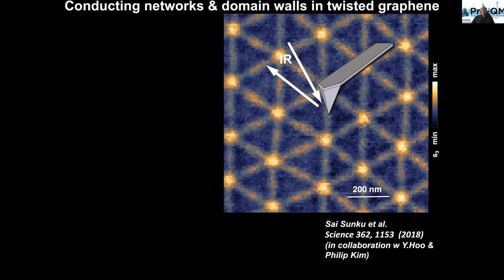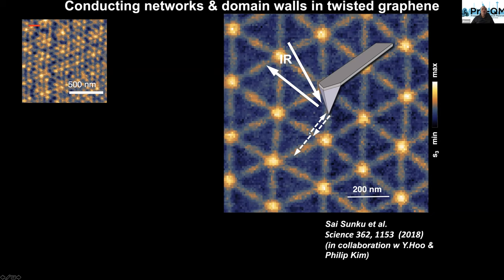And that's very interesting now. So picture this. The tip of the near-field apparatus now launches a plasmonic wave that travels from somewhere towards the domain wall. And then it cannot continue unimpeded through this domain wall because the conductivity here is enhanced. So we have some form of plasmonic impedance mismatch, and there is a probability that this wave becomes partially reflected and some of it will continue to move forward. And if you look at this network formed by domain walls, you see that this is a network of periodic reflectors for plasmonic waves that can travel on the surface of the crystal. And so now if we tune the wavelength of light such that it launches these polaritonic waves, we start seeing fairly complex patterns.